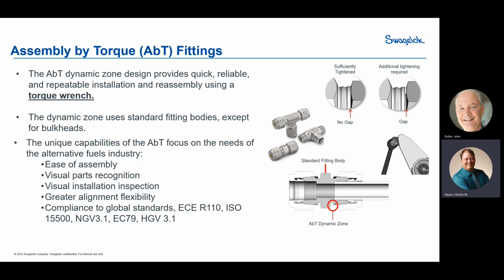We do have an ability to make an assemble by torque two ferrule fitting, basically the exact same as what you see in your normal fitting. All the mechanisms work the same. The physics are all the same, except on the end of the tube, on the end of the nut, we have a crush zone that is in there that allows it to come in, touch the shoulder, and visually be able to tell whether it's tightened well enough because there's no gap, and as well be able to advance and crush more every time you remake it to get up to the standard 25 remakes. And this is assembled by torque with a torque wrench instead of by turns, which is the standard way. The reason we're able to do this is because Swagelok does have the ability to have gaugeable parts.